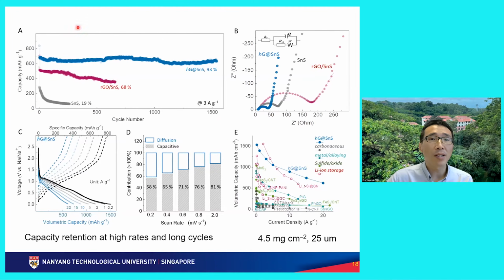Not only cycle life, but also rate performance. It can go to 20 amperes per gram. This is a very high rate performance. If you compare to all the other batteries based on tin-based or silicon-based materials, this is our performance. At all the different current densities, the volume capacity can be very high.